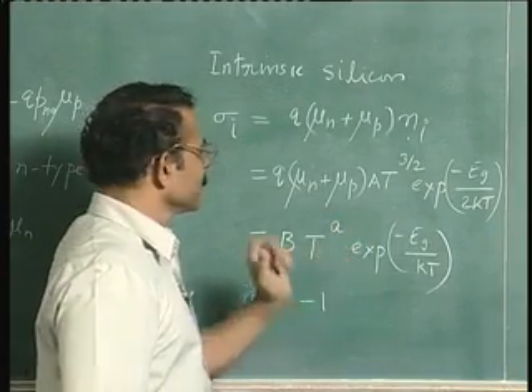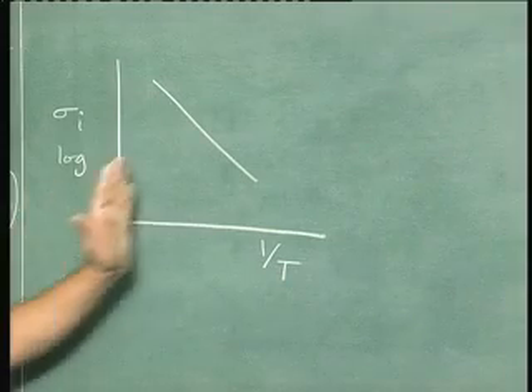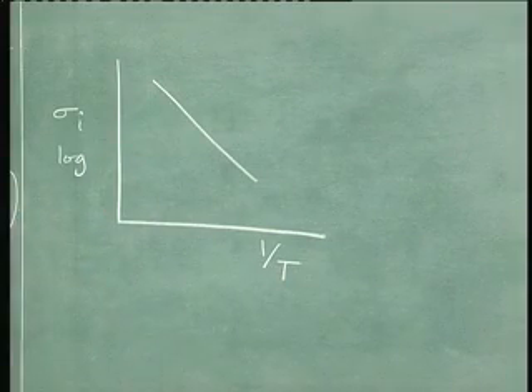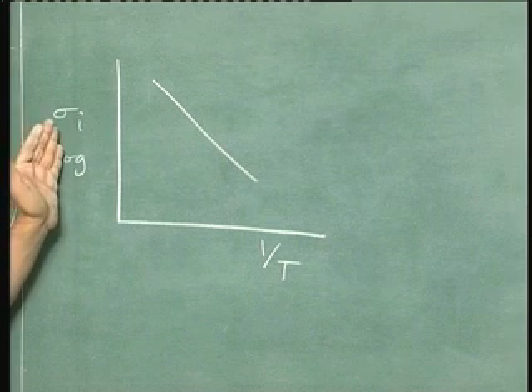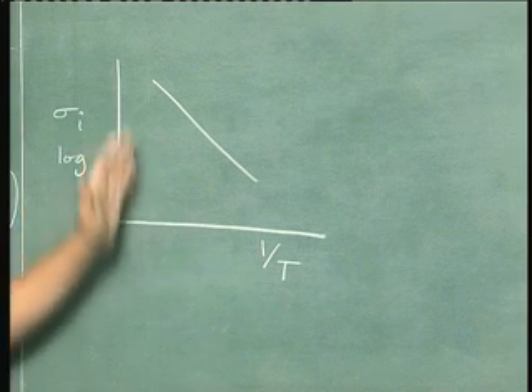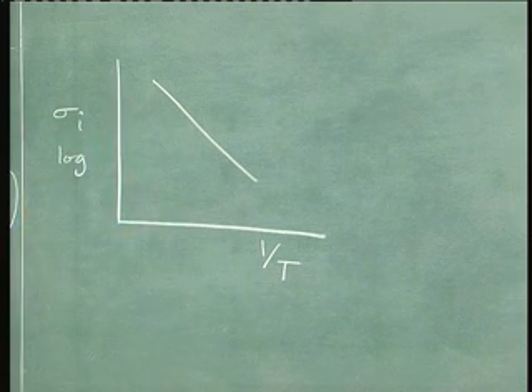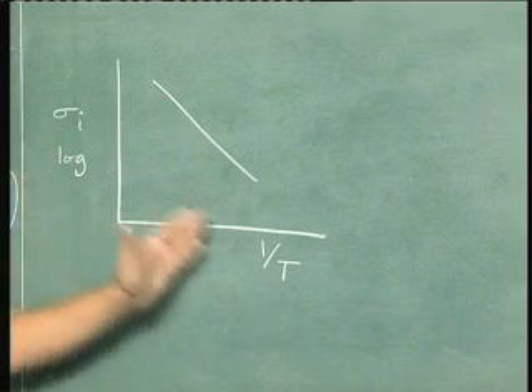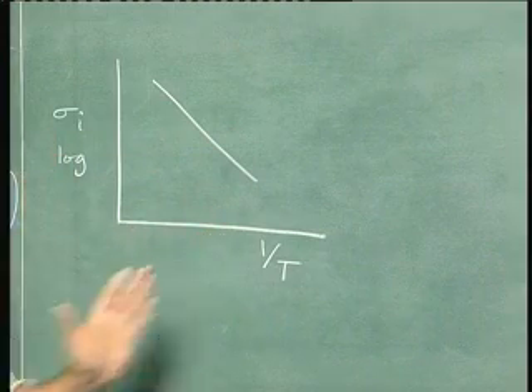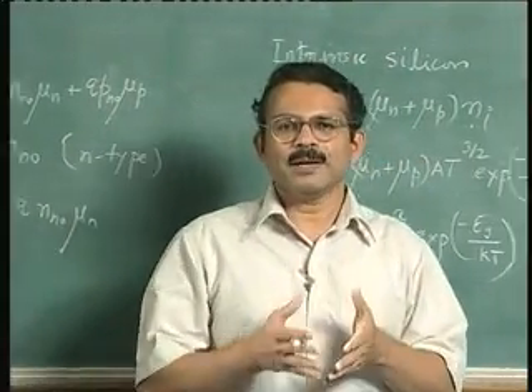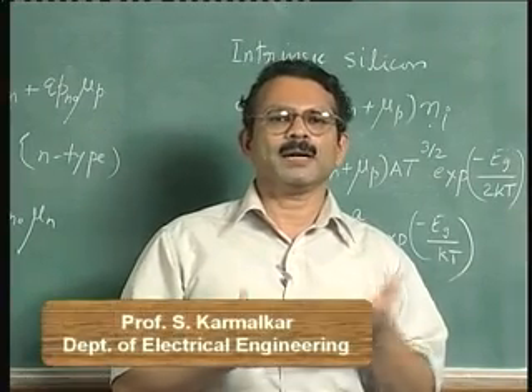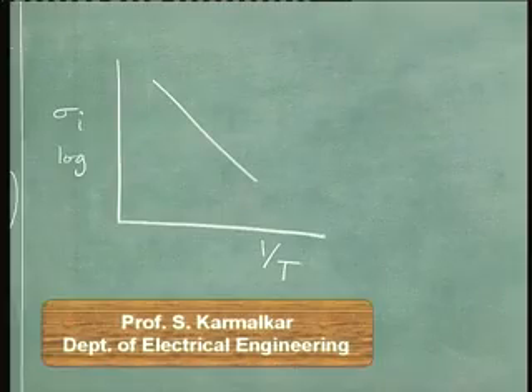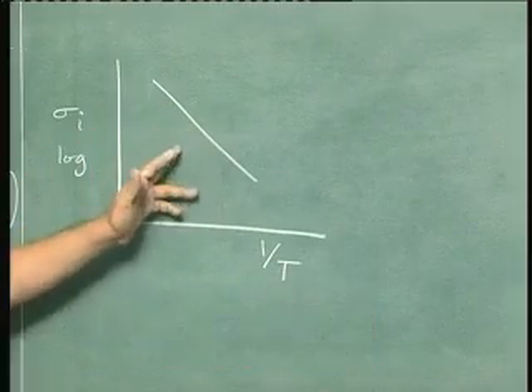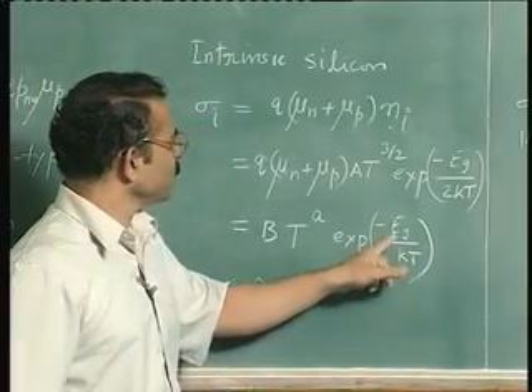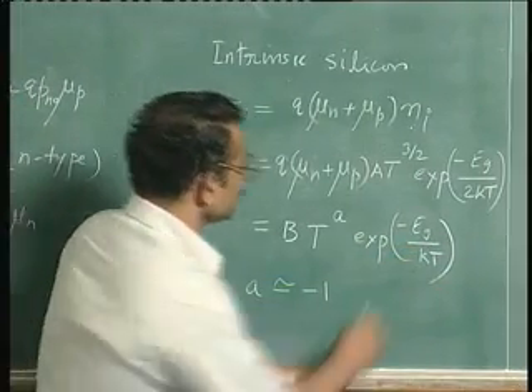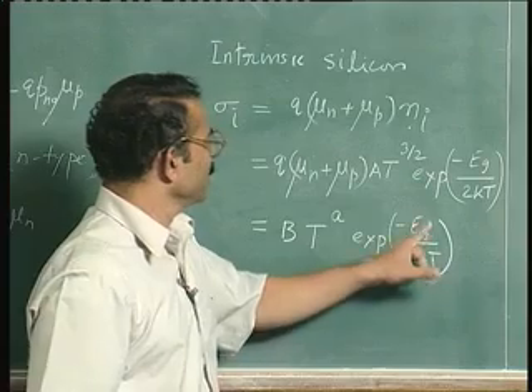And that is why for intrinsic silicon, if you sketch the measured resistivity against the reciprocal of temperature, from the slope of that one can easily get the energy gap, because this behavior is similar to that of the n_i behavior, the intrinsic carrier concentration behavior, multiplied by some constant. Okay. So the slope of this particular line is nothing but, as you can see from here, it should involve 2 times kT.